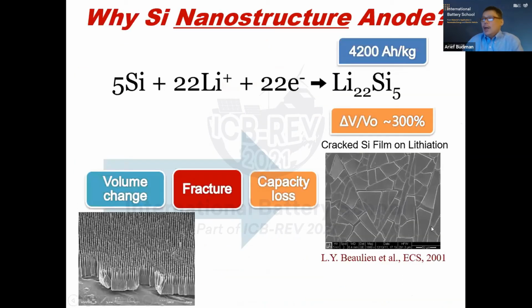Okay, but having said that, silicon is great, but it has a problem. The problem is that silicon is a very brittle material, and with lithium ion coming in, it's being absorbed by silicon. That makes the silicon swell, and it may expand up to a strain of 300%.